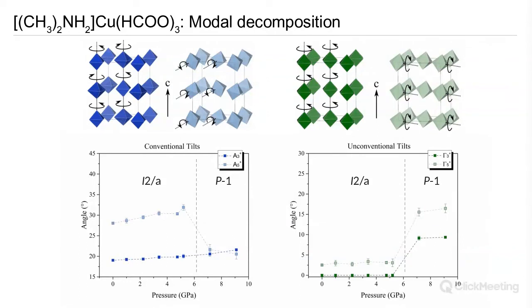And this is informative because it gives us some understanding of how the fundamental normal modes of the structure are responding to the high pressure. So on the left here, I've plotted the conventional tilts. And what we see is that they persist up to high pressures, but we see a small collapse in one of the rotations of the octahedra around one of the axes. With regards to the unconventional tilts, however, despite them being allowed, or at least one family of them being allowed in the low pressure phase, as I alluded to in the previous slide, it appears they really switch on at this phase transition. So they become large and significant in this triclinic phase that appears at high pressure. In this case, I'm describing octahedral rotations that co-rotate with each other, which wouldn't be allowed in the inorganic